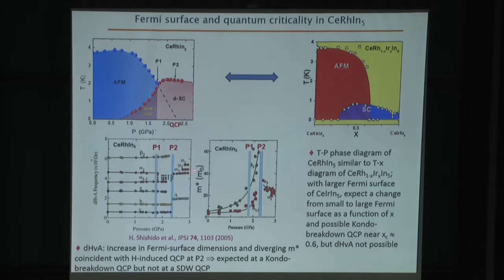So this jump in de Haas-van Alphen frequencies implies that the Fermi surface, certainly of this particular orbit, has become much larger. And this change in Fermi surface dimensions is not expected at a conventional spin density wave quantum critical point, but in fact is anticipated at a so-called Kondo breakdown quantum critical point that involves a critical destruction of the Kondo effect.